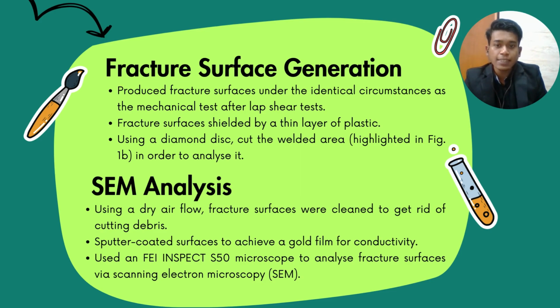Next, SEM analysis. Using a dry airflow, fracture surfaces were cleaned to get rid of the cutting debris. Sputter coat the surface to achieve a gold film for conductivity. Use an FEI Inspect S50 microscope to analyze the fracture surface via scanning electron microscopy.